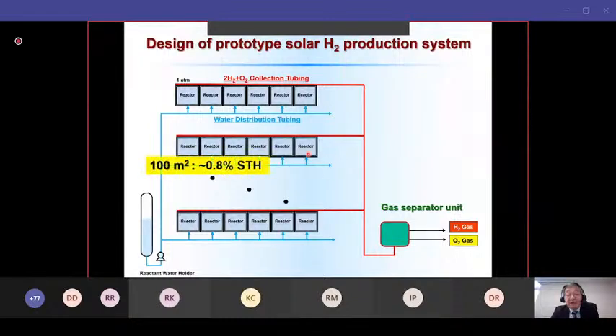So we have constructed this 100 square meter light receiving area. The STH value was about 0.8%, and about 300 liters per hour is the optimum value of gas evolution, and it is enough to test our gas separation membrane.